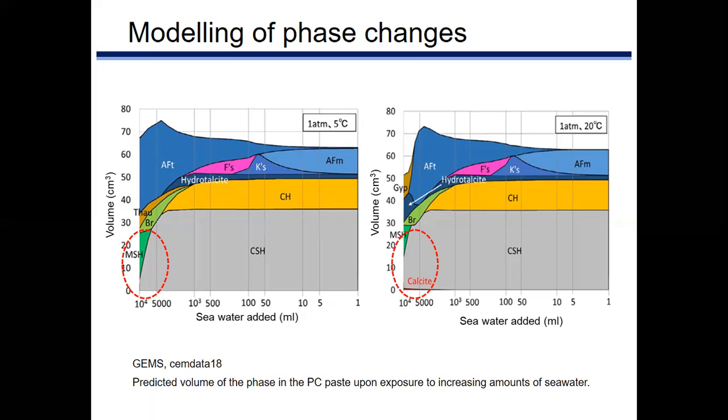We interpreted that deterioration of the specimens could be caused firstly by the leaching of calcium from portlandite and C-S-H and formation of thaumasite, which lowers the density of the specimen surface and/or peels off the surface. And then magnesium ions might infiltrate and M-S-H are formed.